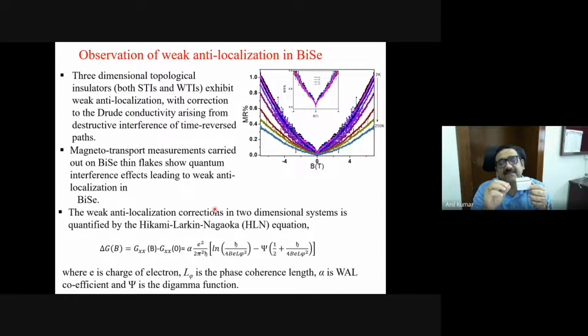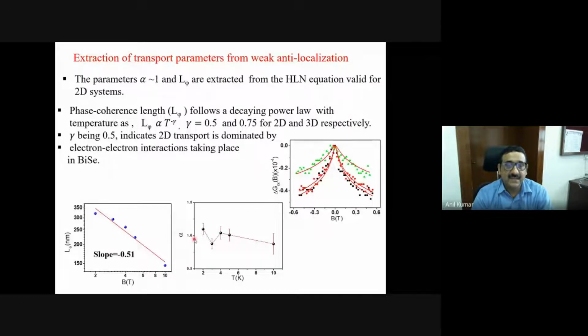And if I have alpha equal to 2, it means the width is very small, and the top and bottom conducting channels are coupled to each other. From there, we calculate and get an alpha value of 1. That tells me that two independent conducting channels are there. And the phase coherence length we extract from that data, and this is the temperature. Then we plot this as a function of temperature, and then we can talk about the conduction mechanism, etc., in this material. So now we have discovered a new weak topological insulator, and absolutely no study on the optoelectronics part is done in this kind of crystal.